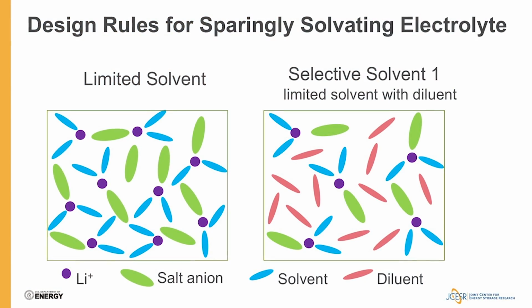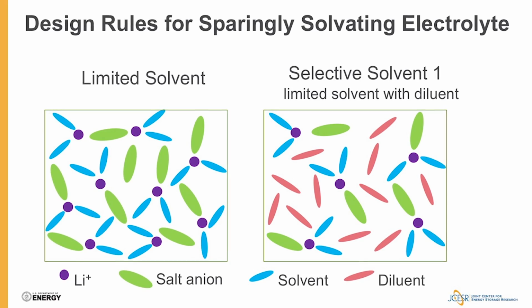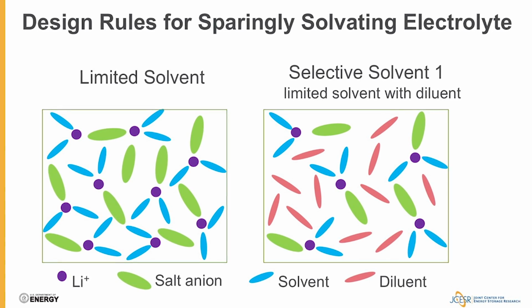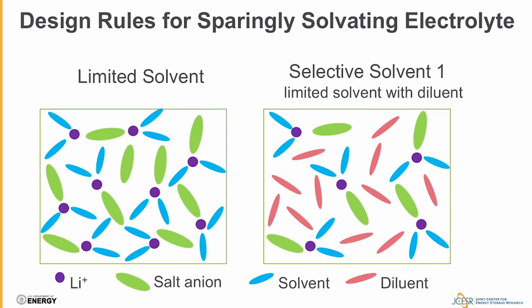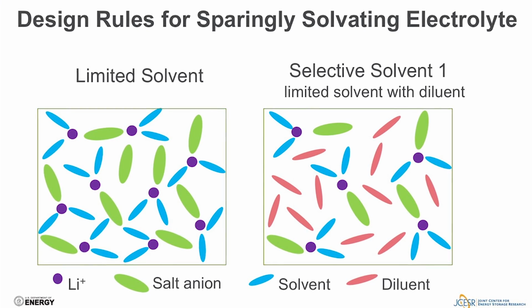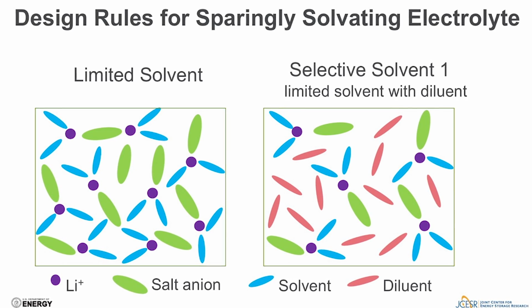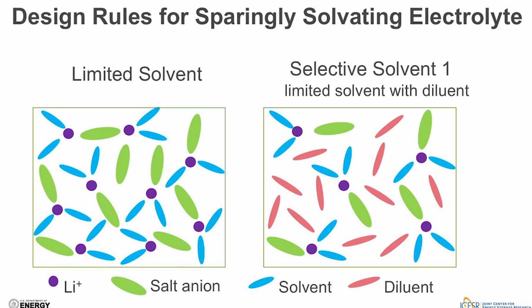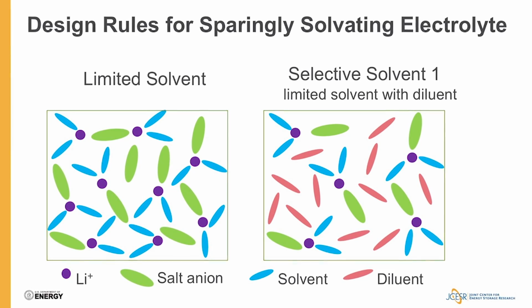The design rules for achieving solubility and mobility of lithium-supporting salt, not lithium polysulfide, fall within the categories of limited solvent and selective solvent. In the limited solvent class, the electrolytes are designed to have a minimum amount of solvent so that the solvents will all coordinate with lithium support salt, leaving none left to coordinate and solvate lithium polysulfide. Designing a selective solvent that overcomes the challenges of the limited solvent can be achieved through three different strategies.